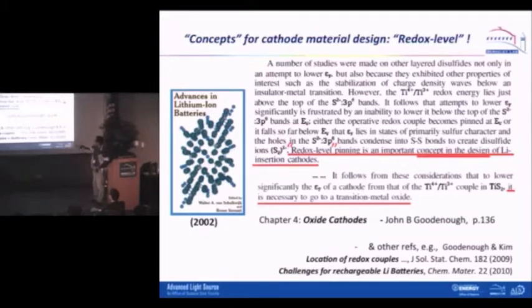So he talks about particular redox level pinning. This idea is very important. He said that before that, it was mainly sulfide material used in the cathode, and following these considerations, we need to go to transition metal oxide. I think most of us know the result of this switch: it is what you are using right now in your laptop and iPhone. He was actually inspired by an undergraduate thesis on lithium nickel oxide, and he invented lithium cobalt oxide. That is what we have been using in the last 2 or 3 decades until now, the lithium cobalt oxide.